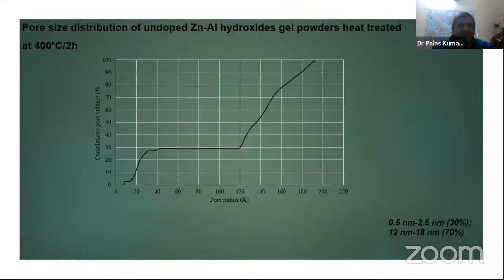This is quite clear. Now, if we see the pore size, the pattern of pore size distribution for undoped and doped counterpart, we see that for the undoped part, 30% of the pores lie from 0.5 nanometer to 2.5 nanometer. Here, the x-axis is angstrom. We convert into nanometer, so it comes to 0.5 to 2.5 nanometer lies within 30% of the total volume, and 12 to 18 nanometer lie with 70%.